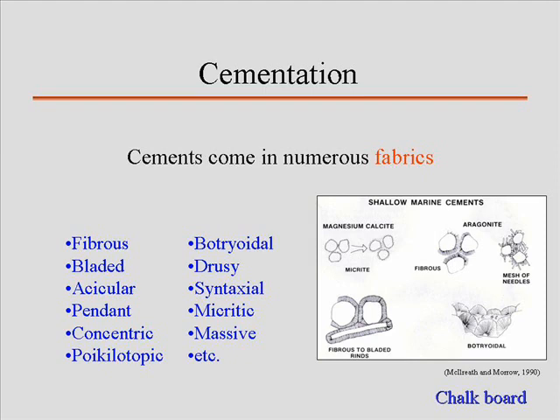If that was all that occurred, if opal was the only cement that filled in this entire rock, what would happen is you'd end up getting a very, very fine looking dusting in the interior of the void space. How could you tell it was opal, by the way? I mean, you can look at the fabric. If you knew what the fabric of opal is, you could identify it that way. But what's the characteristic of opal that would allow you to identify it was opal? Thinking petrography again. When you cross the nicols, it's not going to have crystals. It's non-crystalline, therefore it is isotropic, therefore it goes black and stays black under polars. It will never look like a hole, though, because again it's a form-filling material. So it is isotropic in nature.